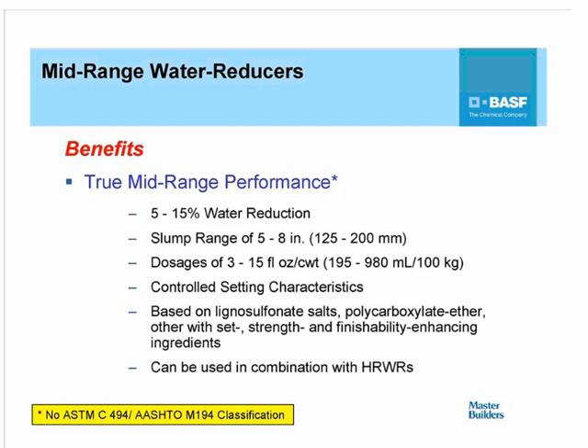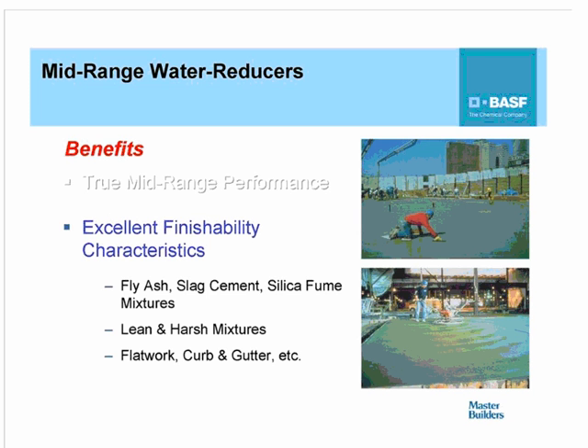The dosages of these materials can range anywhere from about 3 to 15 fluid ounces per hundredweight, depending on the chemistry of the material. And they are designed to have controlled setting characteristics even at the higher dosage levels. And they can be based on lignosulfonate salts, lignins. Some of the newer technologies are based on the newer admixture chemistry, dispersant chemistries, which are the polycarboxylate ether technologies. In addition, most of these mid-range water-reducing admixtures also contain what we call set balances, as well as strength and finishability enhancing ingredients. And they can also be used in combination with high-range water-reducing admixtures to provide synergistic performance.